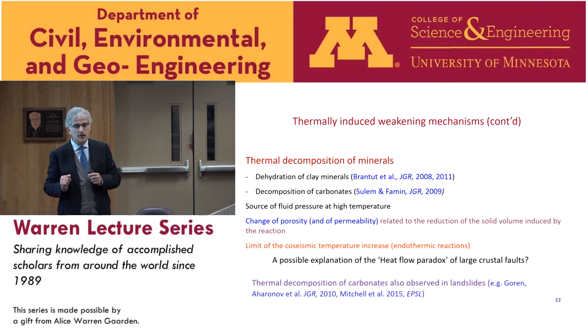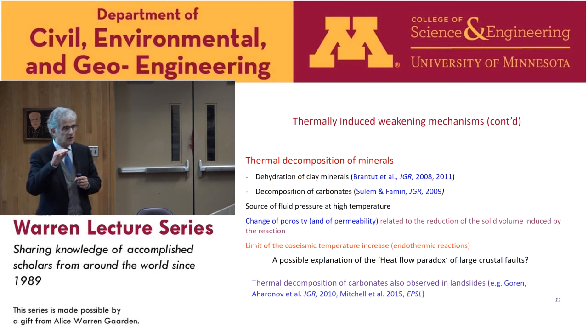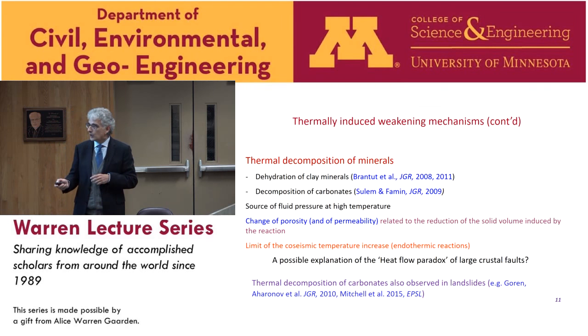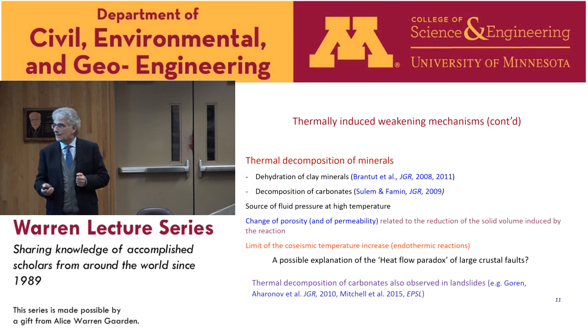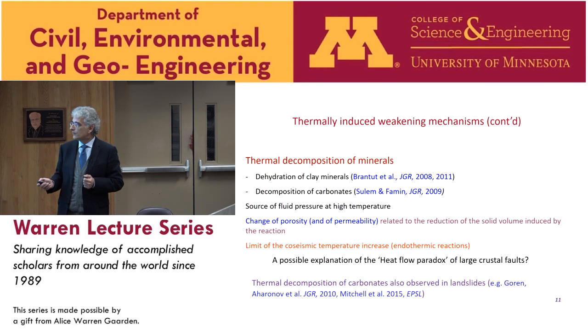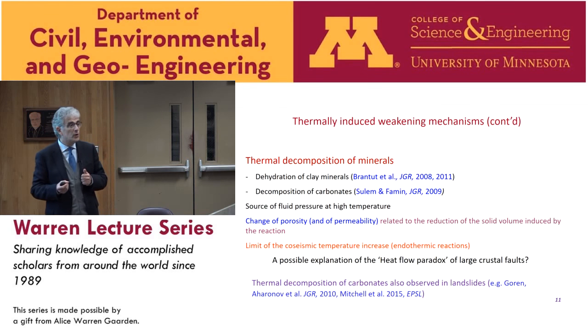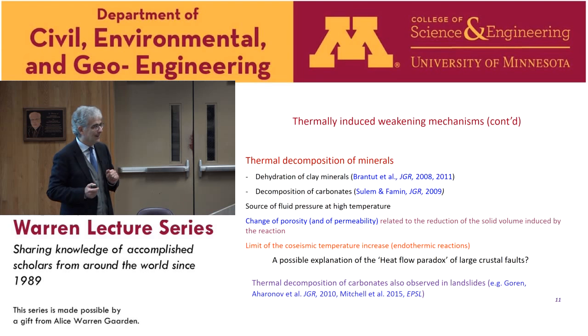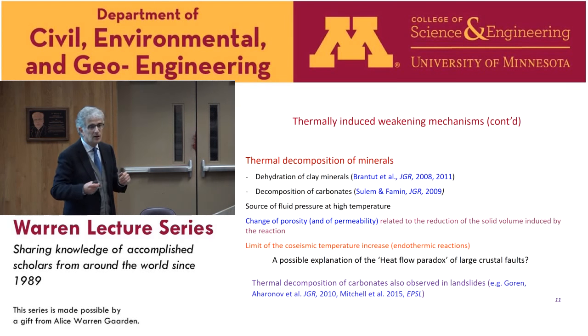As we will see in some simulations, the temperature will remain at the threshold temperature at which the chemical reaction starts. And this has been argued to be a possible explanation of the greatly debated question, what is called the heat flow paradox, the fact that along large crustal faults, we don't see large melted zones, and we do not see high heat flux anomaly.